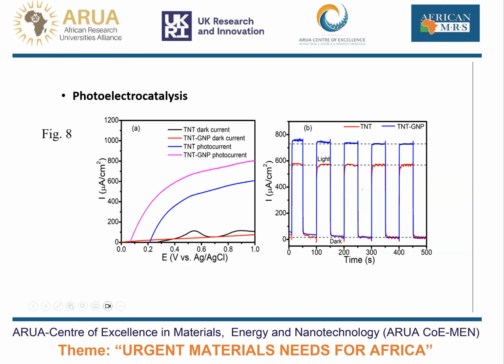Now we check the stability of the system by doing chronoamperometry measurements, as can be shown in figure 8B. It can be seen that the performance is quite stable over a wide range of 500 seconds. As can be seen, the result correlates with that recorded from the voltammograms, as the decorated film has higher transient photocurrent as compared to that of the bare titanium oxide nanotube.